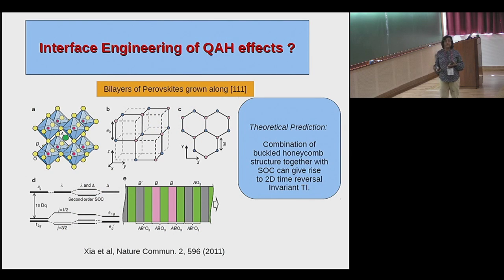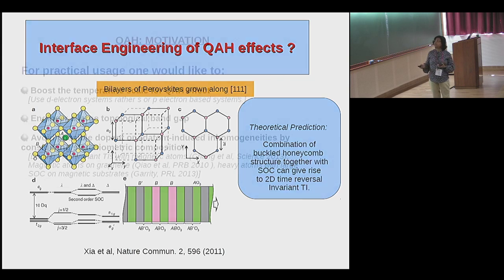Now, there has been a lot of interest in oxide materials in the context of topology as well, especially given this highly discussed paper, which suggested that if you grow the oxide materials along the 1-1-1 growth direction, then the topology is that of a buckled honeycomb lattice. And this buckled honeycomb lattice, together with spin-orbit coupling, can give rise to a 2D time reversal invariant topological insulator. So that brings back the attention to the oxide materials even in the context of topology.